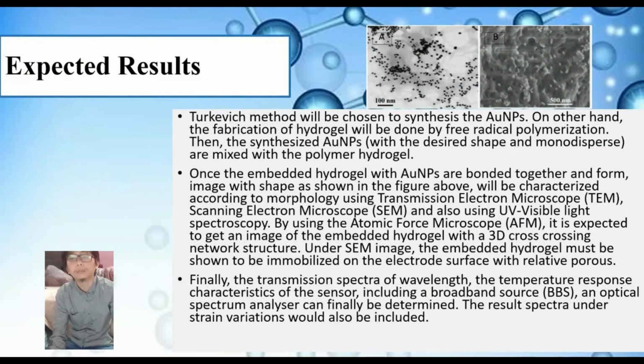characterized according to morphology using transmission electron microscope (TEM), scanning electron microscope (SEM), and also using UV visible light spectroscopy. By using the atomic force microscope, AFM is expected to get an image of the embedded hydrogel with a 3D crossing network structure. Under SEM image, the embedded hydrogel must be shown to be immobilized on the electrode surface with relative porous.